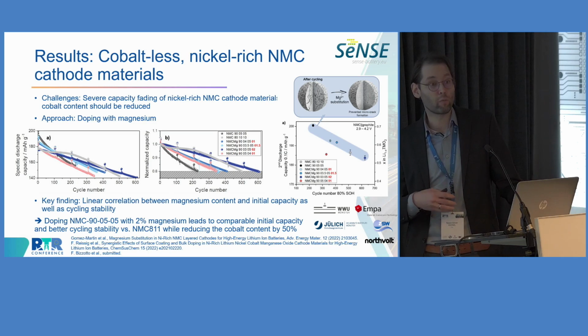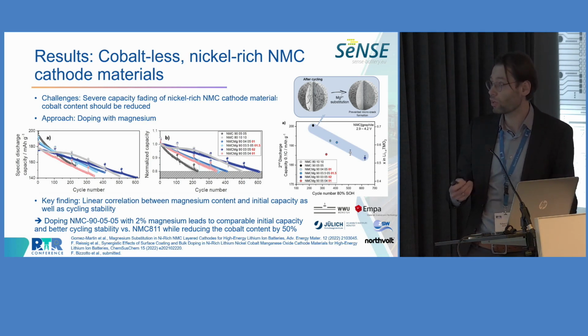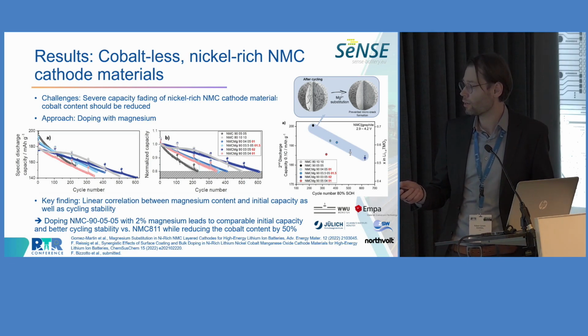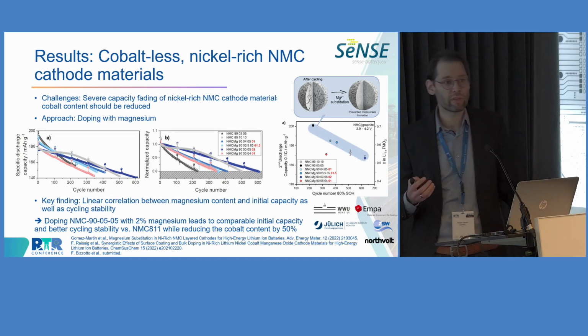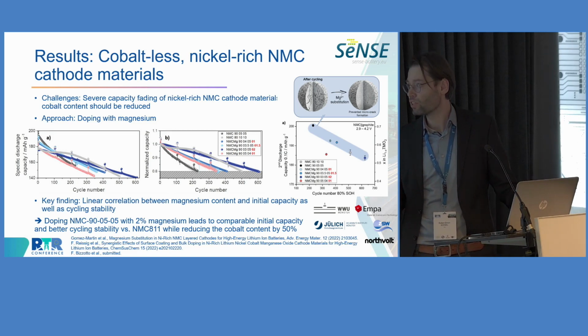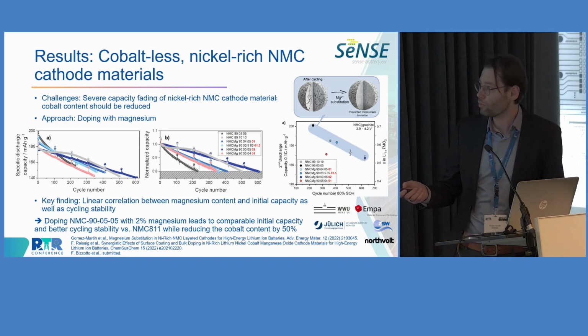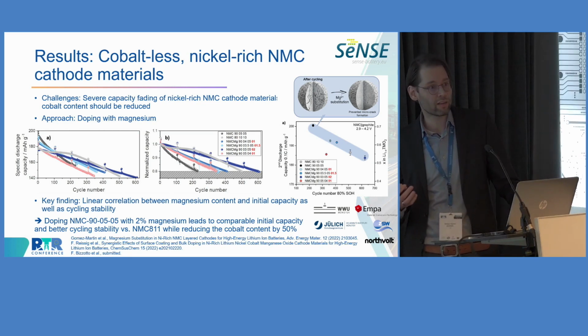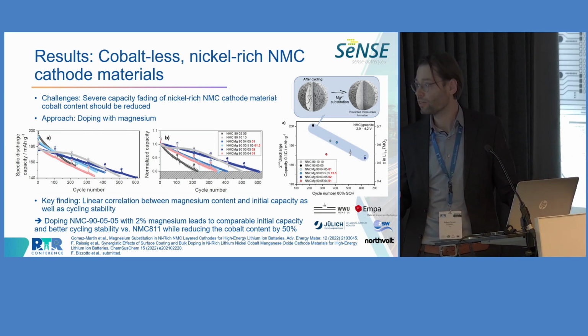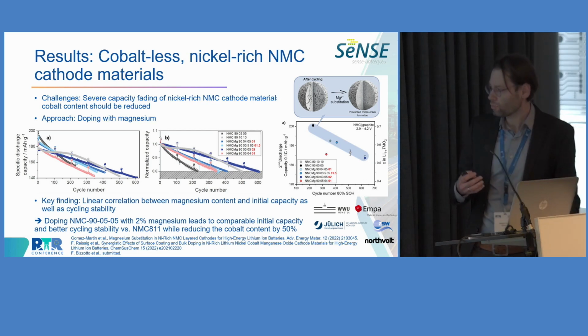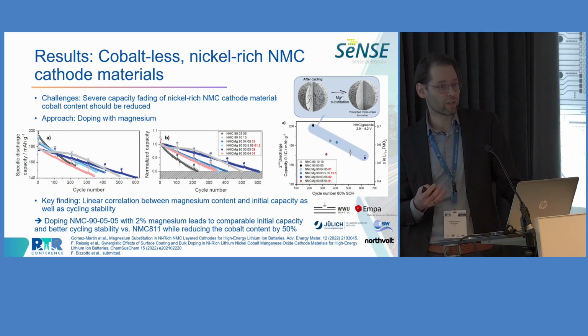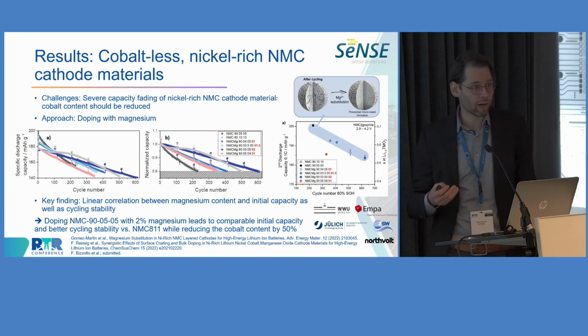So we have been exploring different approaches to improve the cycling stability, including dopings and coatings, and also working on the electrolyte. And in this example that was published last year in Advanced Energy Materials, we try to substitute some of the cobalt by magnesium. And what is quite interesting, when you put 2% magnesium inside the material, you end up with a material that has a comparable or even slightly better cycling stability than NMC 811, here in dark blue, with similar initial capacity, while we are reducing the cobalt content by 50%, which is really important, right? And at the moment, we are upscaling NMC materials for the second generation prototype. So this is a work of our partner ZSW that is doing the upscaling.